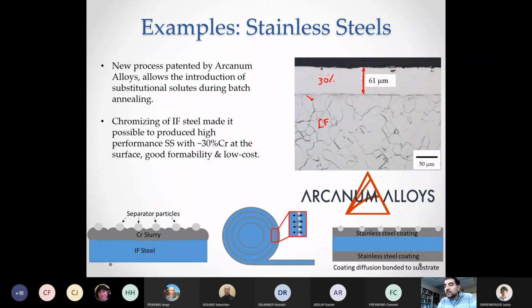So the process that Arcanum developed is a very interesting one where they take the cold rolled steel coil, the full coil, and they apply a slurry that contains usually a chloride of the element they want to deposit, so chromium chloride, for example. They paint that on the coil, and then they coil again. So it becomes a tight coil like this. And they put it into the batch annealing furnace. And after a long time, it's 20 to 40 hours at high temperature in the batch annealing furnace, the chromium chloride reacts with the hydrogen in the furnace atmosphere.